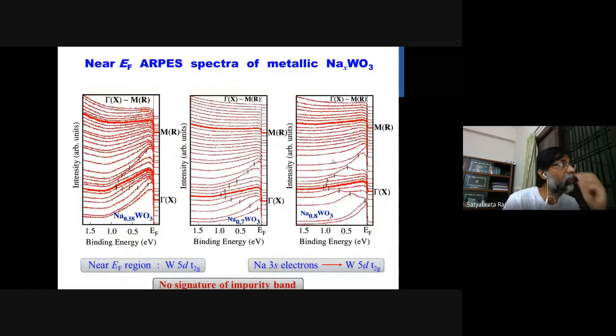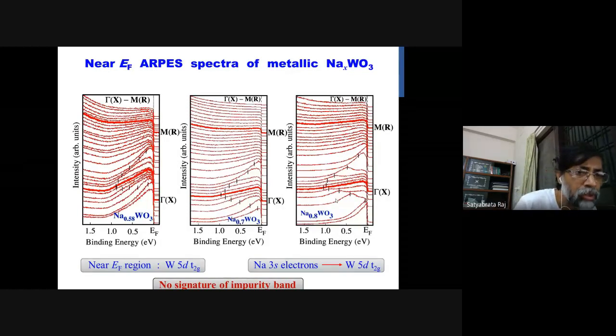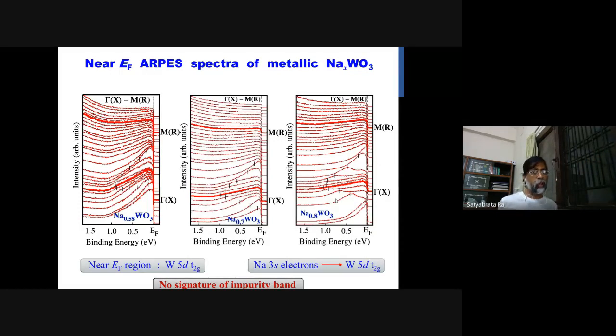So let's go to the very low energy spectra of the near, and you can see the band is actually moving from here and making an electron-type band, and we don't see any impurity band. Just like in a semiconductor with an electron-doped material, it gives impurity bands, we don't see any sodium-induced impurity band. So by that way, we discard the formation of the impurity band in this system.